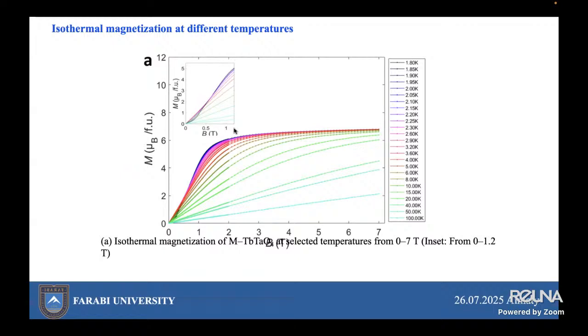And at low temperature, for example, you see that between 1.8 and 2, maybe on this region, dark blue to pink curves, the magnetization increases rapidly with field, saturated at just more than 6 Bohr magnetons on this parameter, and isothermal magnetizations indicating ferromagnetic-like behavior with the spontaneous alignment of magnetic moments.